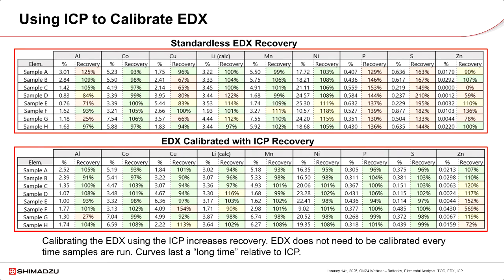The top box is the standardless EDX recovery. Notice for elements like aluminum, sulfur, and phosphorus, the recovery is quite poor, or in other words, the degree of correlation between the EDX and the ICP is quite poor. However, when you use the ICP to calibrate the EDX, the recovery improves, as indicated by, for example, the green colored boxes in the aluminum, phosphorus, and sulfur columns.